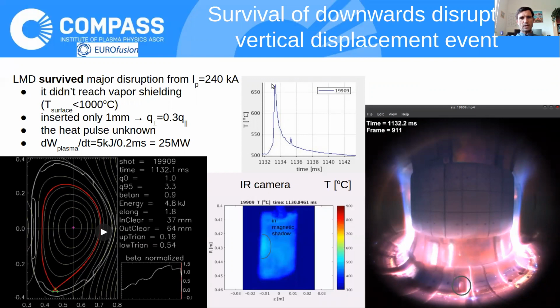The surface temperature rose by 150 degrees during this short time, which is also visible here by the infrared camera. It was not exposed strongly, only this tiny surface, and only 30% of the parallel heat flux went to the surface. But it was at least interesting to see that it was not damaged by this disruption.